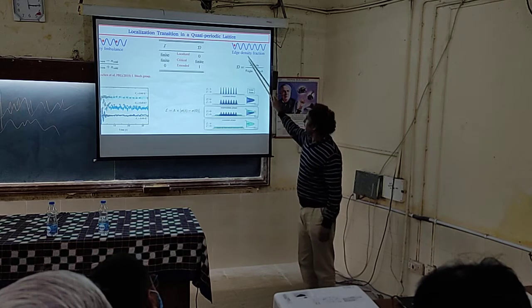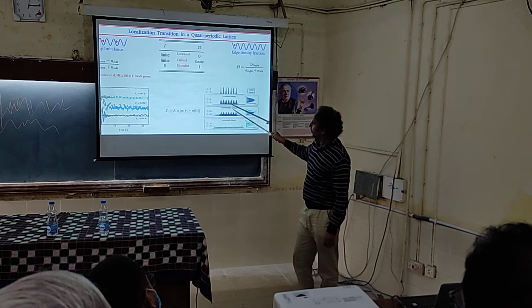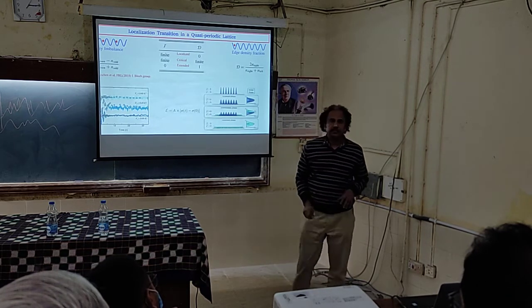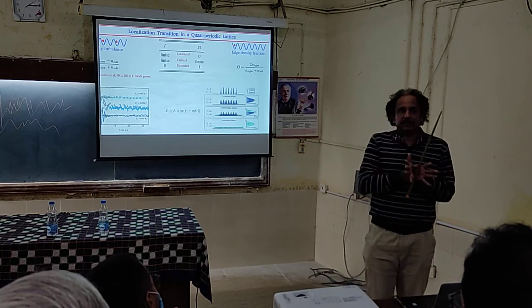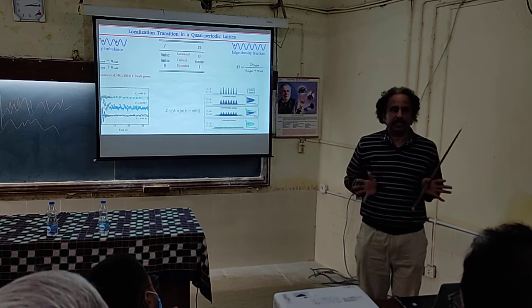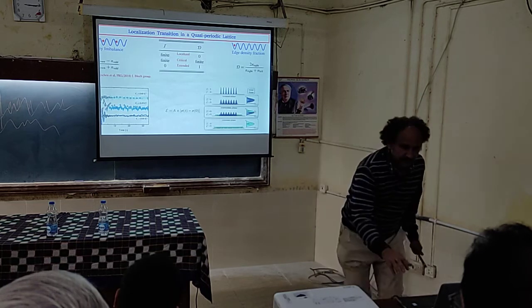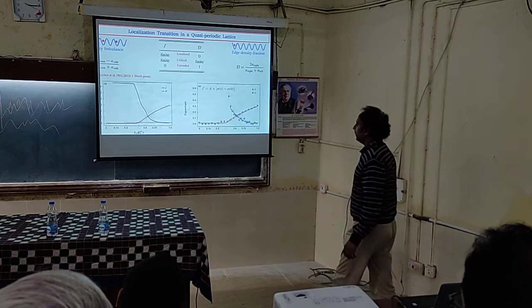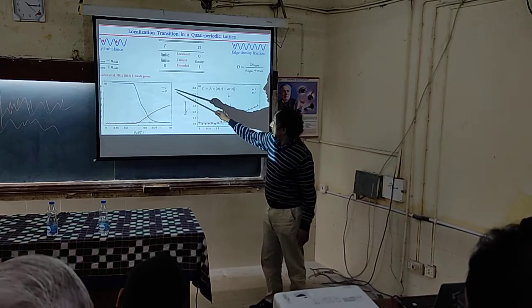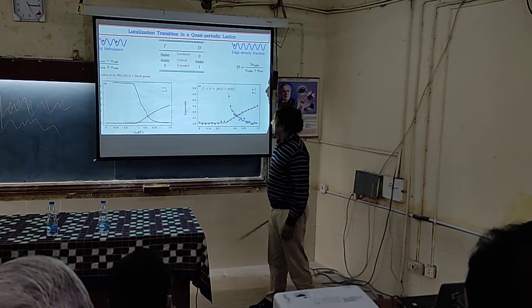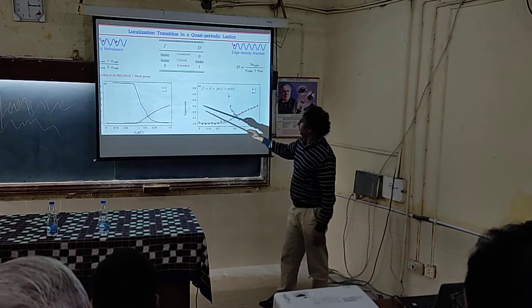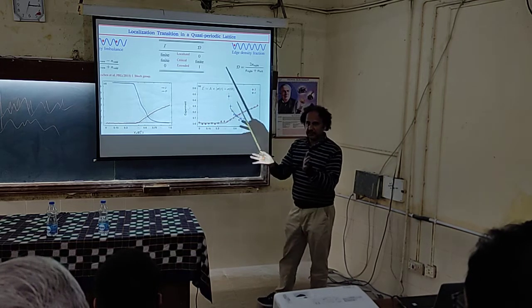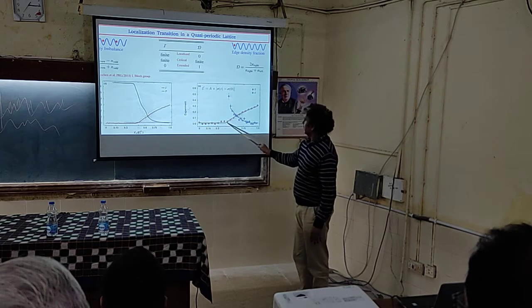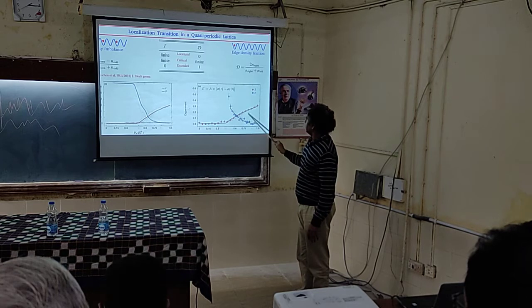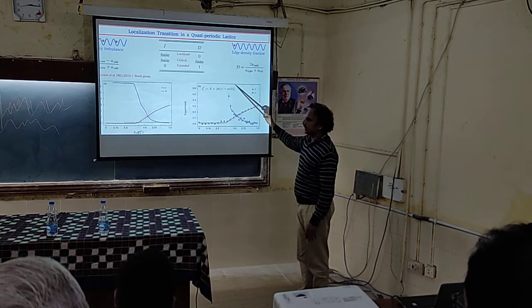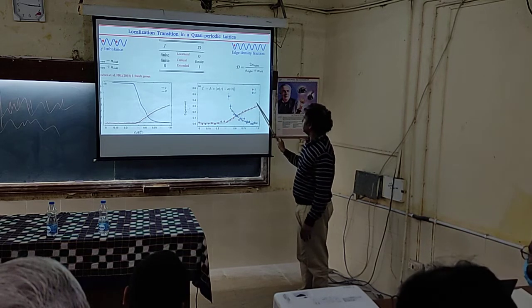Okay? So directly in the experiment, this quantity cannot be observed. So what they detected in their experiment is this mean square displacement. What is the spreading distance of this wave packet? They computed this and they found this very beautiful experimental observation here. So you can see this is your imbalance, this is your D, and this is the theory, and here is the experiment. In the experiment they obtained this mean square displacement, which is E, and the imbalance. Imbalance is 0, then it is finite. On this side E is 0, and in this region both are finite. So this is a critical phase, this is extended, this is localized.